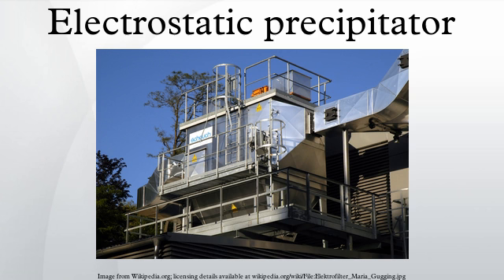Disruptions of the normal corona process greatly reduce the ESP's collection efficiency, which in severe cases may fall below 50%. When back corona is present, the dust particles build up on the electrodes forming a layer of insulation. Often this cannot be repaired without bringing the unit offline.